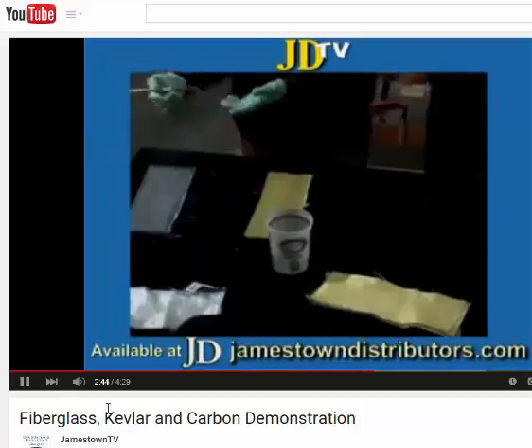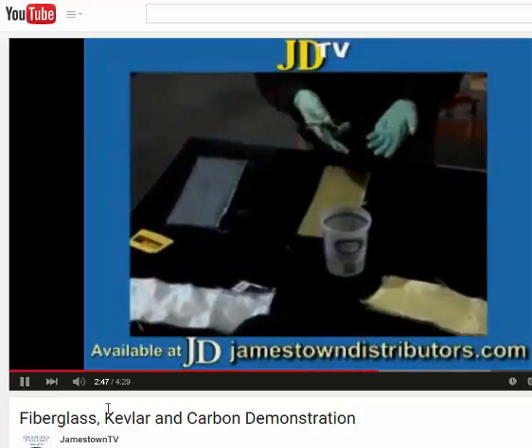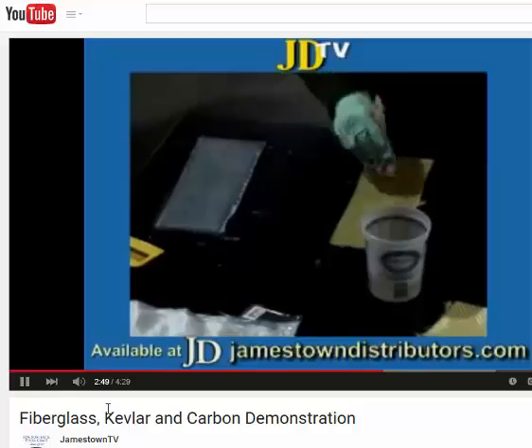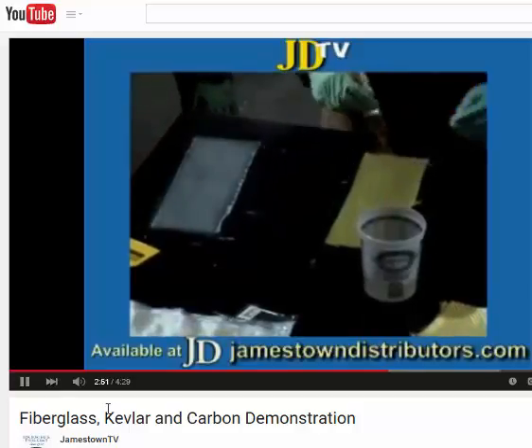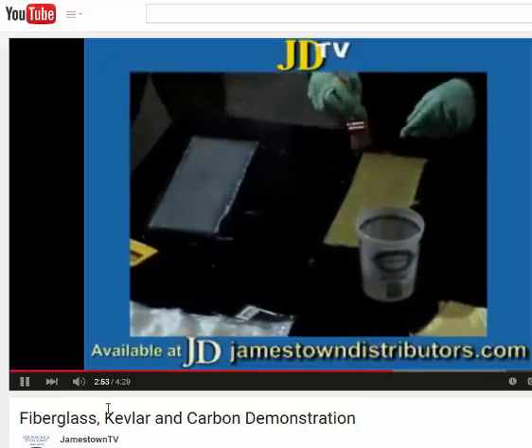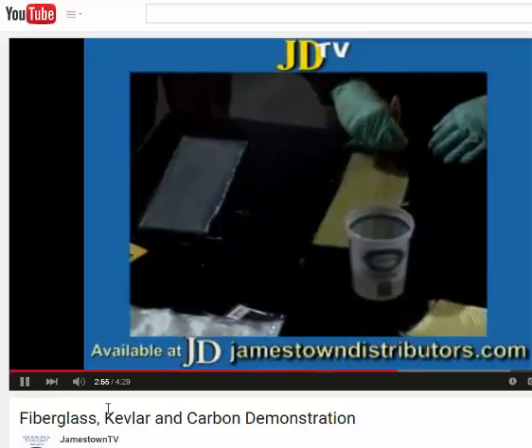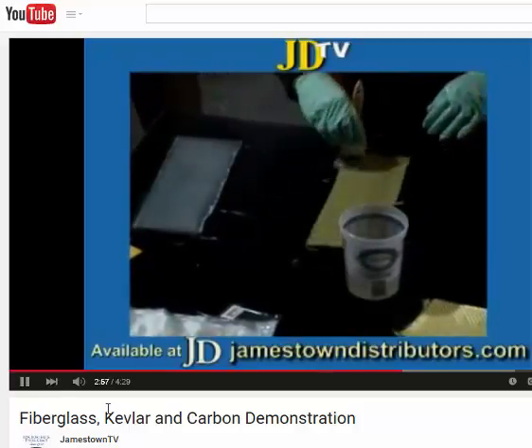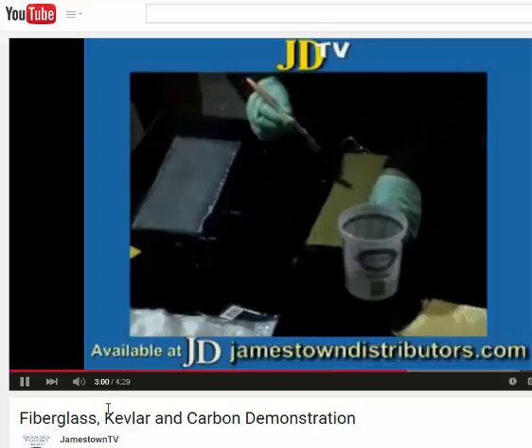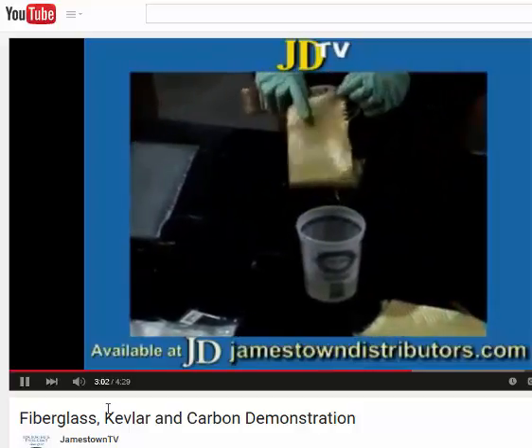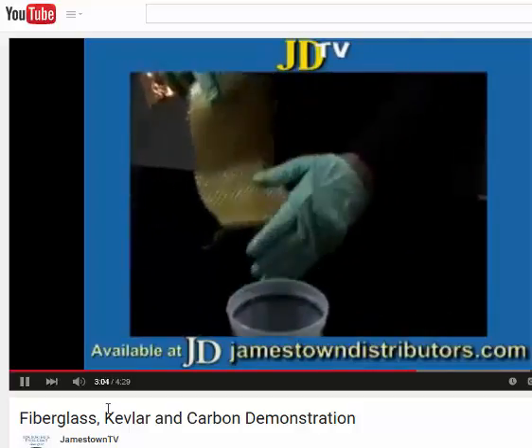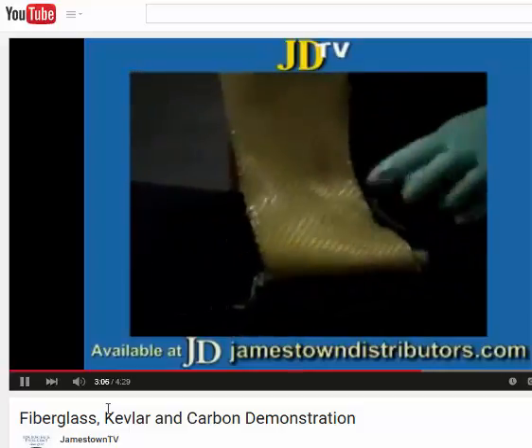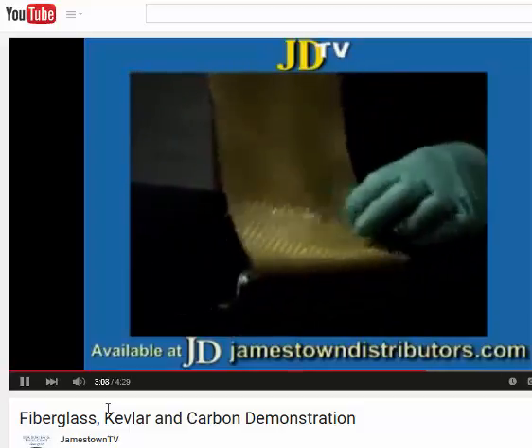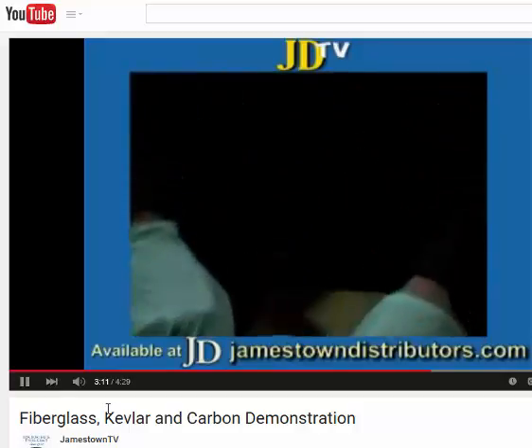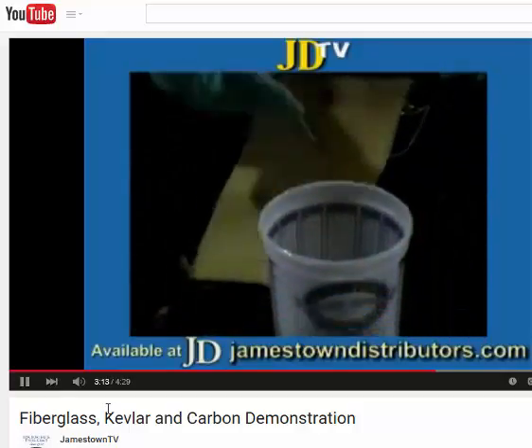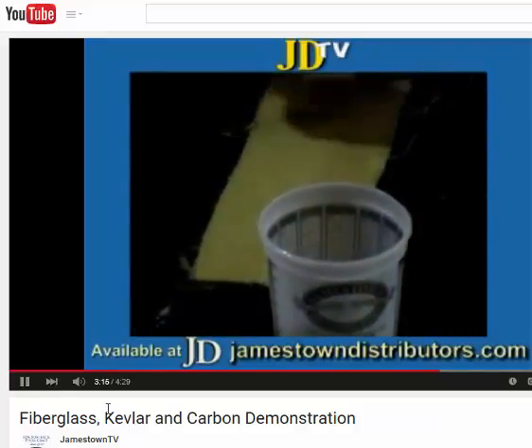Yes. There's a difference between wetting out glass and wetting out Kevlar. It's a lot more difficult to feel comfortable doing a good job. But you can peel that back and you can see that the combination of having the substrate, the table pre-wet, and ensuring that you've got a lot of resin there, that's how I feel comfortable knowing that you've got Kevlar properly wet out. Obviously, there's more resin than you need, but I'd rather be on the safe side with Kevlar.